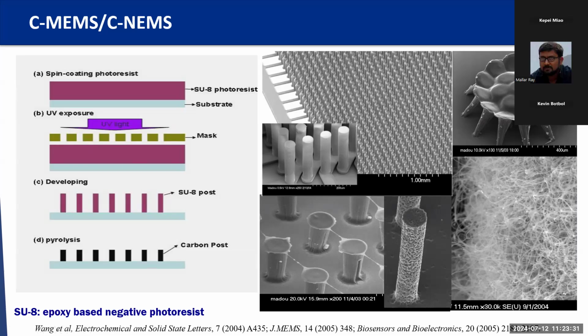You can see if we use SU-8, this very unique negative photoresist, we can build high aspect ratio carbon arrays. In this case, we can easily build 20:1 to 50:1 aspect ratio. I will show you some pictures from when we worked at UC Irvine. We made the first generation 3D batteries, and we also made glassy carbon suspended nanowires by changing the ramping speed. If you want to do the carbonization fast, you raise the temperature quicker than the normal recipe. You can also get very porous carbon structures.